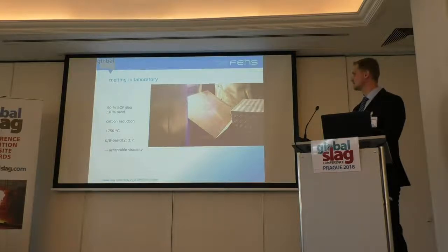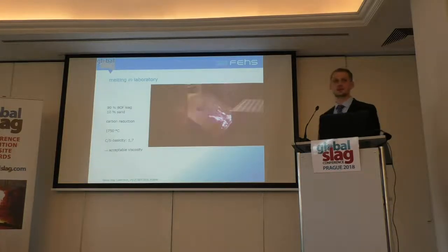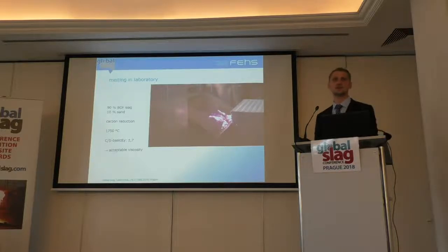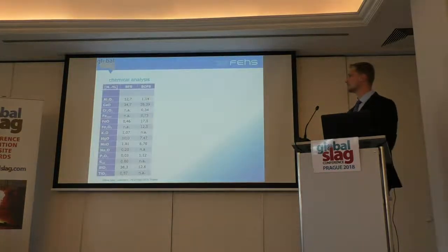But as you can see here, the slag was in the first moment very liquid, everything okay, but due to the cooling of the crucible when it's out of the furnace, we are below the 1700 after a few seconds. And so we had the same problem, about 50% remains in the crucible, we're not liquid and we don't get it out. So this means in a big scale, when you have a problem in the steelwork and the slag pot has to wait for the further treatment, 1 hour, something like this, you are losing the temperature and you get the same problems.